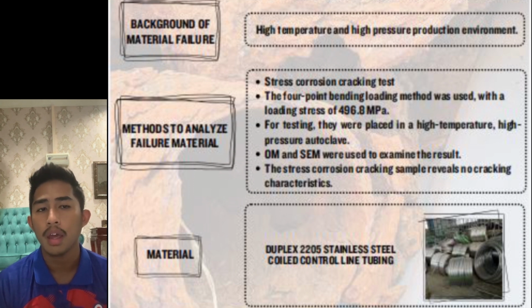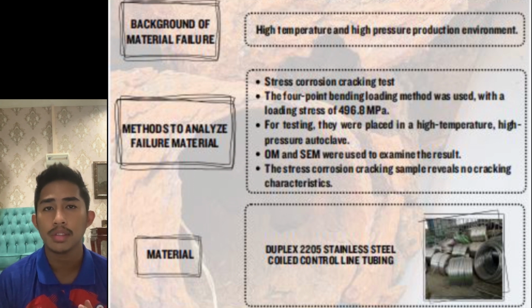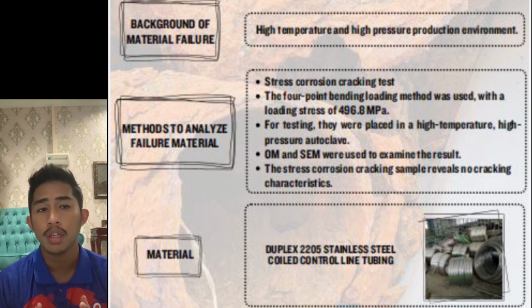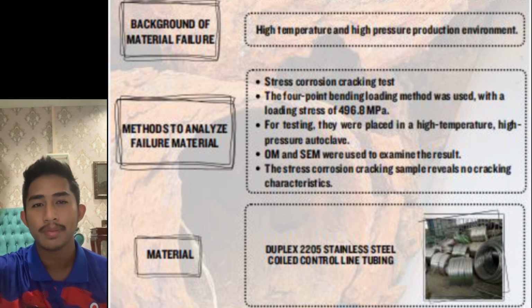The longitudinal sectional analysis of the stress corrosion cracking sample shows that no cracking features are found, and the high magnification SEM, which is the scanning electron microscopic image, further shows that no cracking has occurred at the bottom of the corrosion pit, which indicates that the 2205 duplex stainless steel has excellent stress corrosion cracking resistance in the simulated formation water containing H2S and CO2. That's all for me. Thank you.